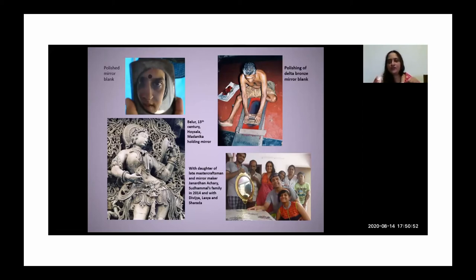So basically the polishing process is of lapping, going back and forth on this polishing board. But another very interesting step which the craftsman revealed to me is that they actually used a crushed and powdered alloy, the polishing powder itself comprises powdered alloy of the mirror itself. So you see that, and as you can see, that's why it looks very silvery there. What that plays is a certain self-polishing role. So if there are flaws, then the same alloy goes in and fills in those flaws. So that's why you get such a brilliant finish, really. And there's several days of lapping it and so on, and then it's finished.